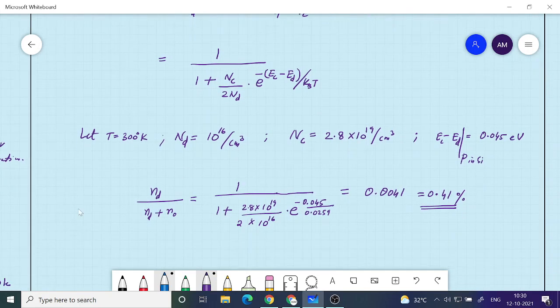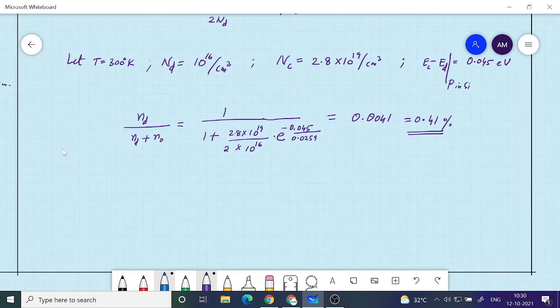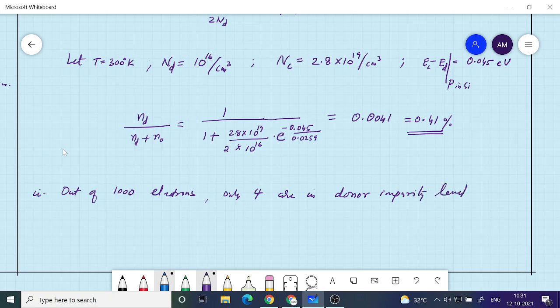That means the occupancy of the donor level is very, very small, fractionally very, very negligible. Out of the total electrons, if you look at this number, out of say 1000 total electrons, only 4 are in the donor level. Only 4 of them are in the donor impurity level. And all the remaining, that is 996 electrons out of the 1000 at room temperature, are in the conduction band.